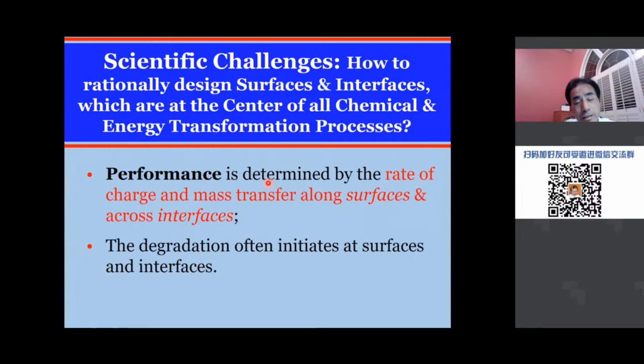Another reason is that when we're talking about durability, we want the fuel cell system to run for at least 5 years or even for 10 years. But the degradation often initiates at the surface and the interface. So unless we have a good control of surface and the interface, we will not be able to get the performance, nor the durability we're looking for.